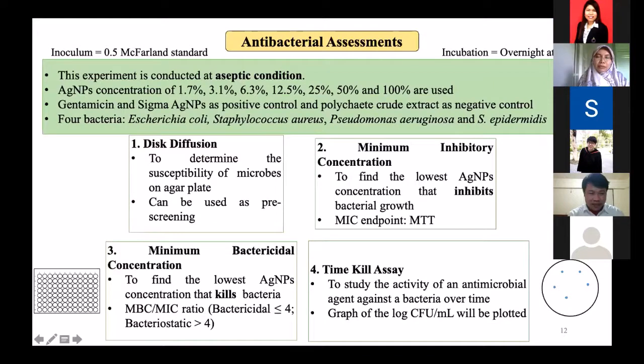After the silver nanoparticle characterization and validation, we now move on to the antibacterial assessment. For the antimicrobial study, we just focus on antibacterial tests. As I mentioned to you, we use 4 types of tests here: disc diffusion, MIC, MBC, and time kill assay. We use concentrations from 1.7% up to 100%. We use 2 types of controls in this study. We use gentamicin for the antibiotic control. We also use silver nanoparticle commercially purchased from Sigma. And we also use a polychaete crude extract as a negative control.